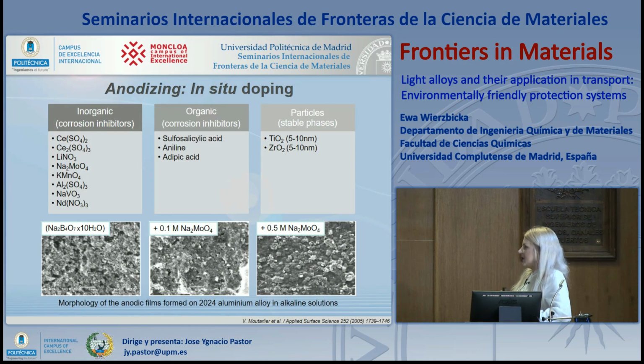We can modify the electrolyte by simple in situ doping, so by adding some small amount of some substances that can be in inorganic form or organic form and provide the corrosion inhibitors to the coating. Also, we can use particles which are very stable phases, like titanium oxide or zirconium oxide. Presence of these species also might affect the morphology of the final coating.